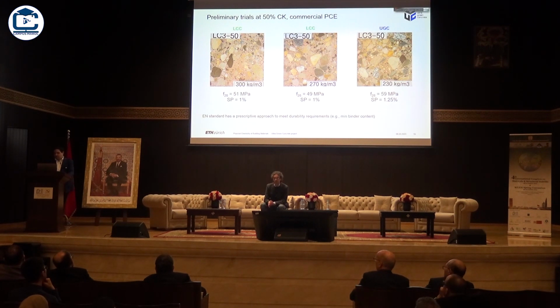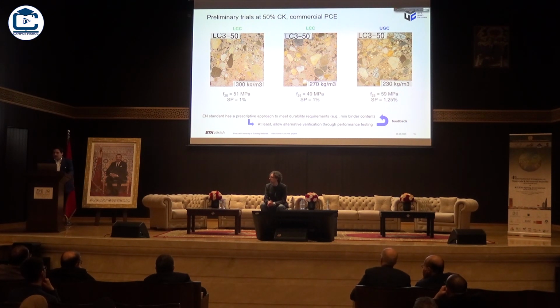And the problem is that these kinds of prescriptive tables do not allow us to move into low carbon concrete materials. So I think that since changing standards is something that takes time, definitely we need to do it. At least we should allow, at the minute, alternative verification through performance testing. So allow people to do low carbon concrete and validate their exposure and durability performance through testing. And the interesting part is that probably the outcome of this testing can feed back into the standard, and we can enter into a more extended discussion of how we change the standard into a performance-based qualification for durability requirements of concrete.